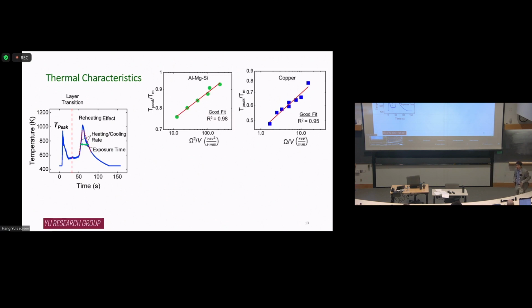Just one example showing here. Basically we are mapping inside the processing parameter space. We look at aluminum alloy 6061 and copper, and we linked the peak temperature with a so-called pseudo heat index, which is a function of my processing parameters, right? So this is just an empirical relationship, and you can develop that for specific materials. For aluminum, we figured out omega squared divided by V is a pretty good empirical pseudo heat index, which is consistent with the previous work on friction stir welding. For copper, we figured out omega divided by V is a better term, and that's probably because copper has a very different contact state and material flow behavior.